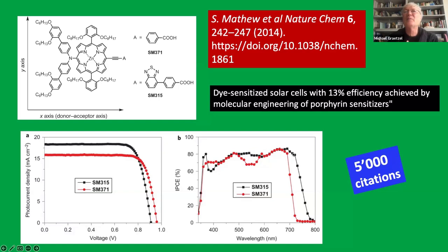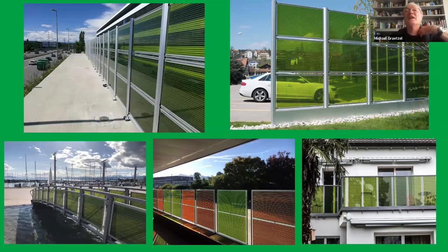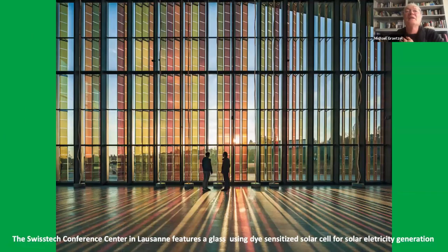Sometimes we even get 90%, and so the dye is as good as a top-notch quality silicon cell in terms of visible light harvesting. But of course, we use much less dye, and the production of those dye molecules is much cheaper. And so here's some, before I pass to the perovskites, here's some of the commercially produced panels.